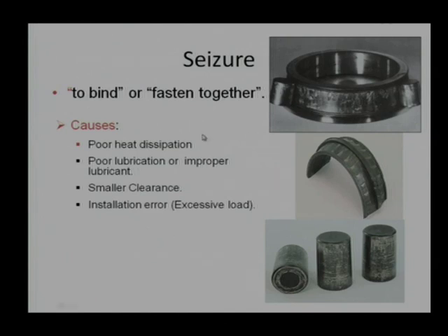However, there is another chance that lubrication was not proper. The system was designed keeping in mind that lubrication will work, our lubricant will work, the lubrication mechanism will be active. But maybe because of a power supply or pump failure, lubricant was not delivered to the bearing surfaces or tribo surfaces. In that case, what will happen? There will be a jump from a low coefficient of friction to a high coefficient of friction. In the lubricated case, we kept a coefficient of friction at roughly 0.05, and when lubricant stopped getting delivered at the interface, the coefficient of friction increased to 0.3, 0.4, 0.5, 0.6.